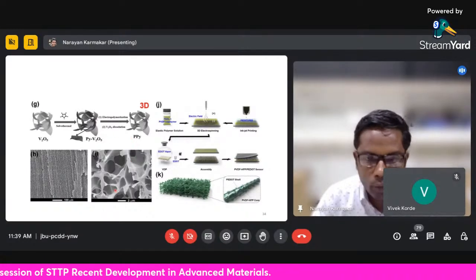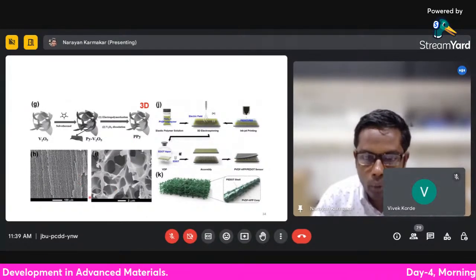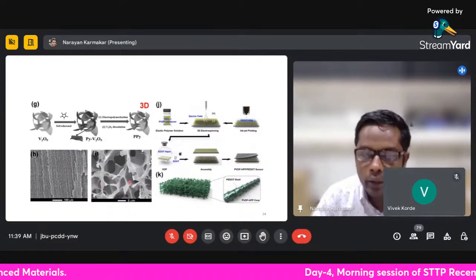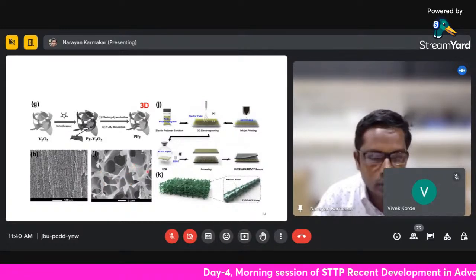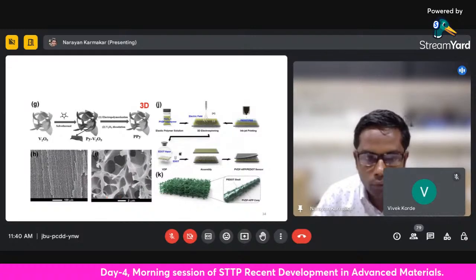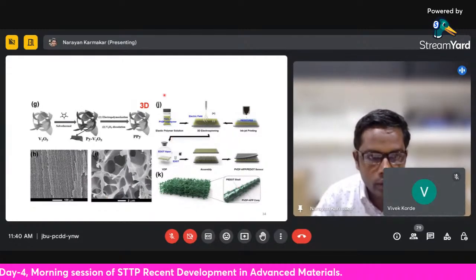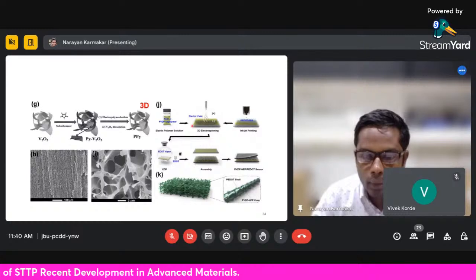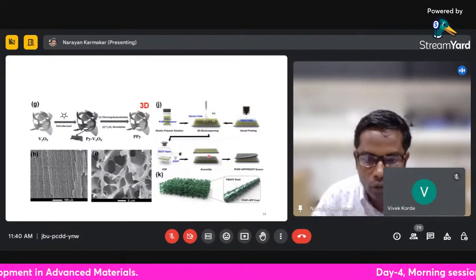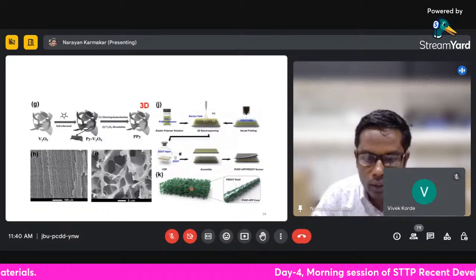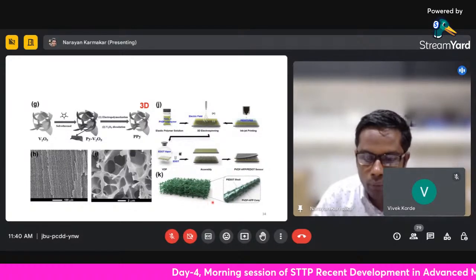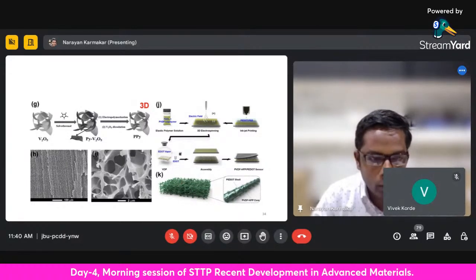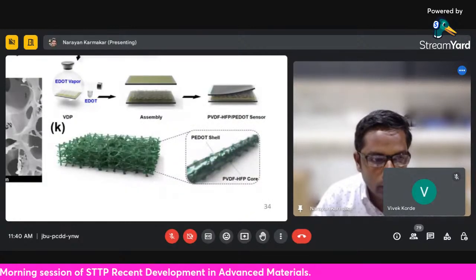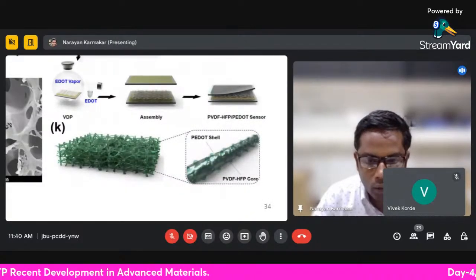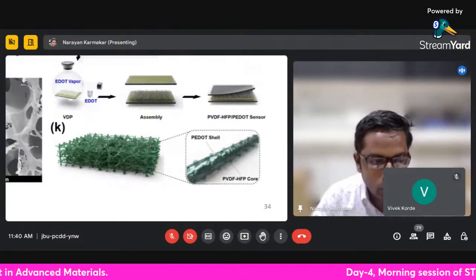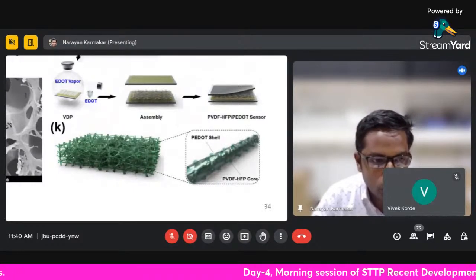And this is the scanning electron microscope image of the PVA PPY composite, which is impregnated with a boiling HCl aqueous solution and then freeze dried. And in the figure J, we can see the manufacturing process of these PVDF-HFP/PEDOT sensors. And finally, at the figure K, we can see the 3D nanostructure PVDF mesh fabricated by electrospinning. If you look at this image, it is the electrospun PVDF-HFP/PEDOT nanofibers, and we can see it's a very highly porous structure.